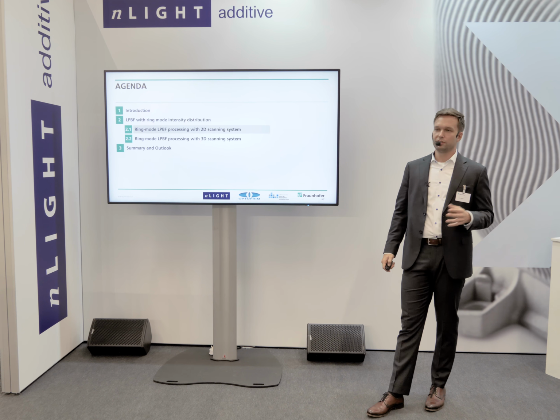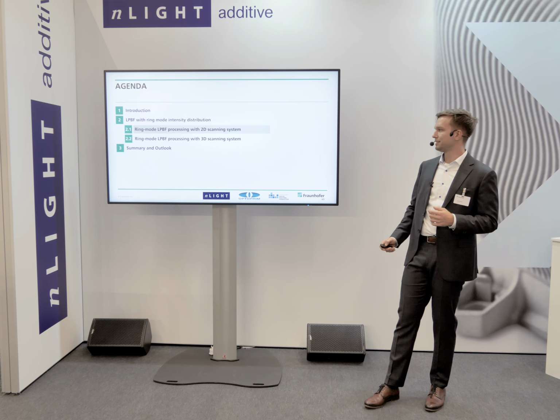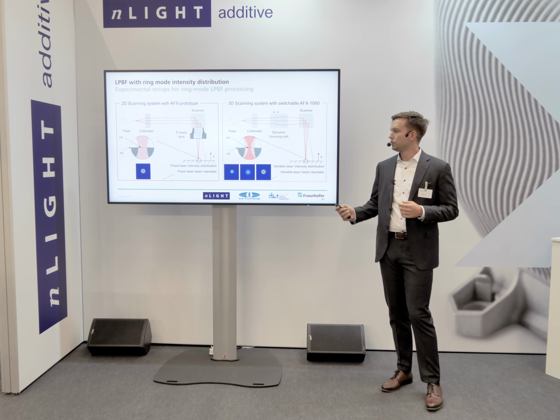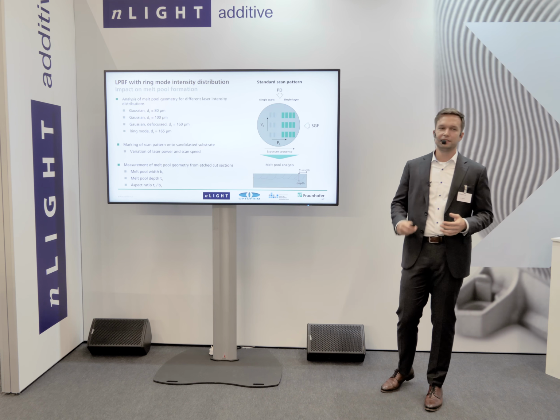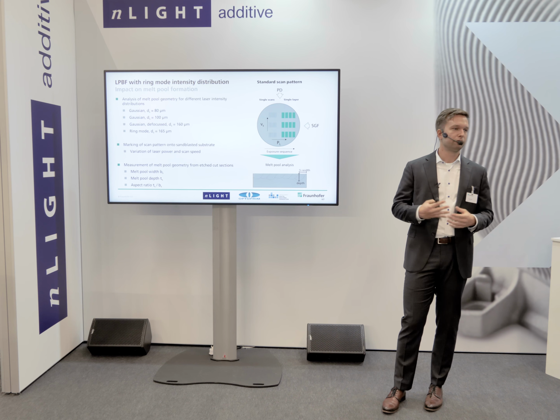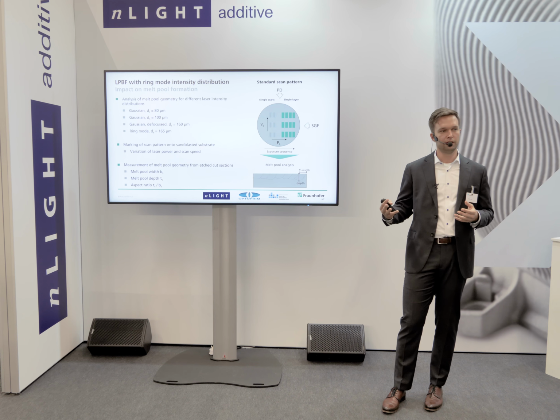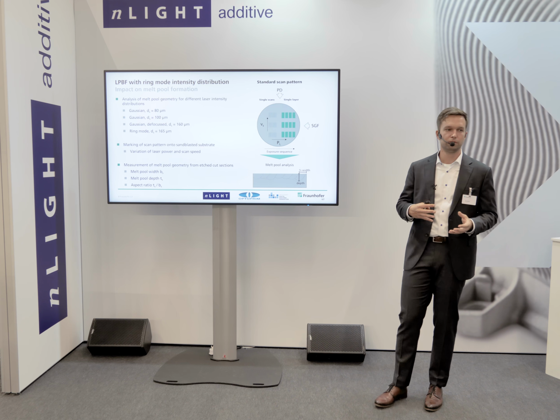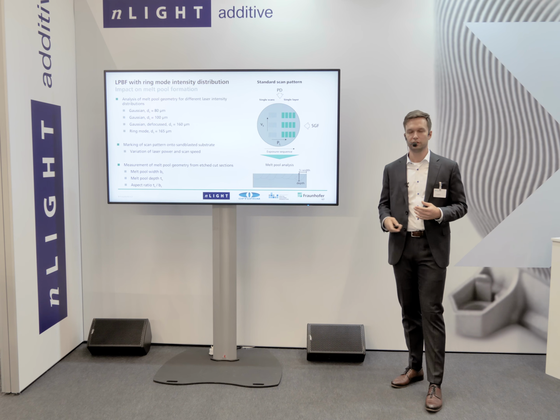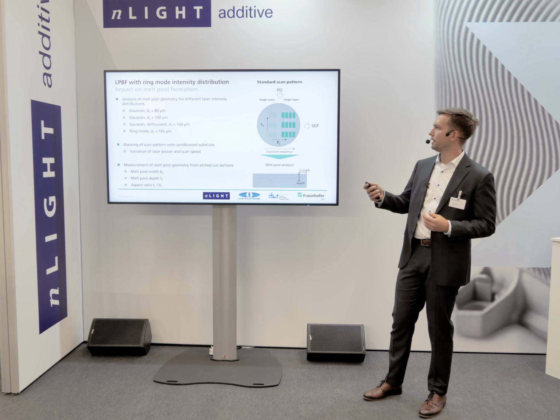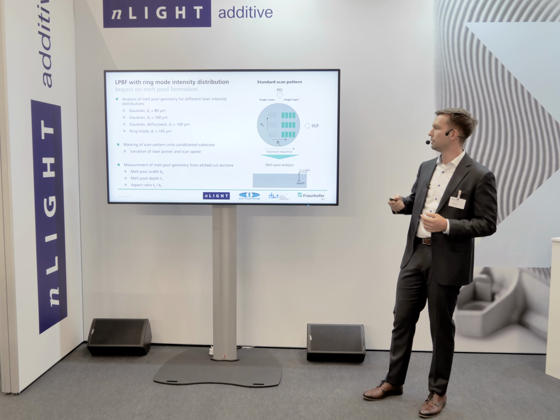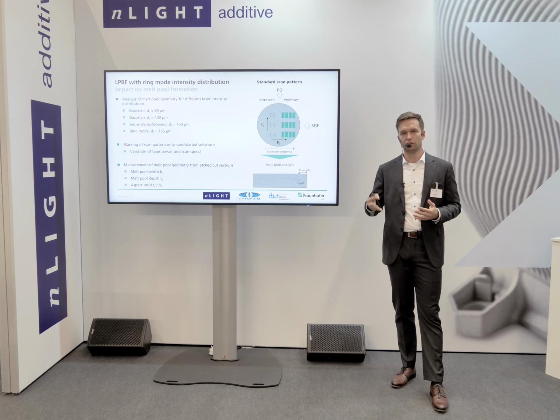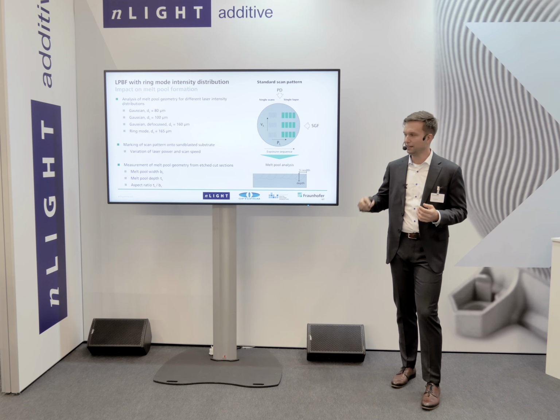So at first, as I mentioned, we started with a 2D system, to investigate how the melt pool behaves and how it forms when you use a ring-shaped intensity distribution compared to single-mode Gaussian. We did some kind of standard scan pattern consisting of several scan lines and also interconnected single layers.